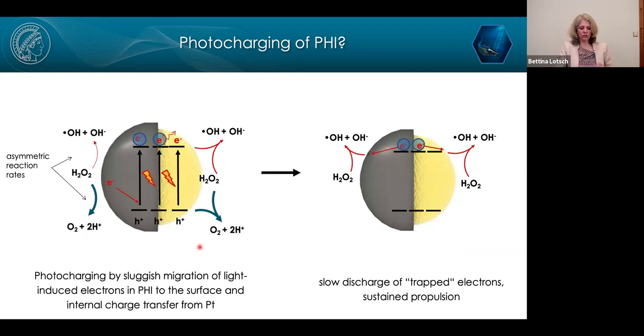But coming back to the question, can we actually observe something like photocharging in these systems? Can we charge them up in the light and then make them move or continue to move in the dark? There's one scenario where we could imagine that this happens. We need a buildup of electrons on PHI, in spite of the fact that we have oxygen around that can act as an electron acceptor. Normally one would assume that once there's oxygen around, the blue state is not maintained because the electron is simply taken up by the oxygen.